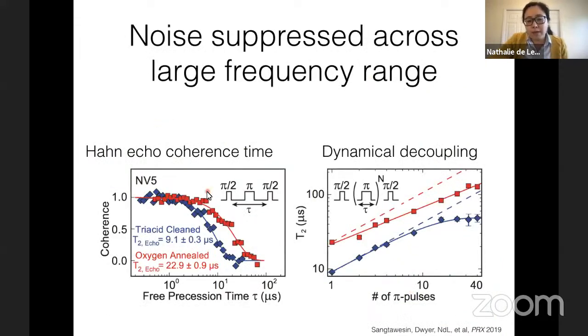So from the point of view of the NV center, we can look at the coherence time, and this is on a log scale, and we can see that after we do this last oxygen annealing step, we get an improvement of a little more than a factor of 2.